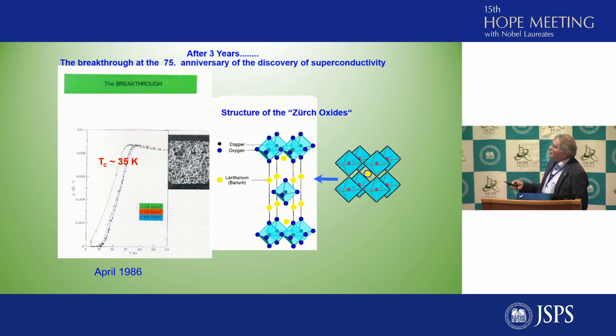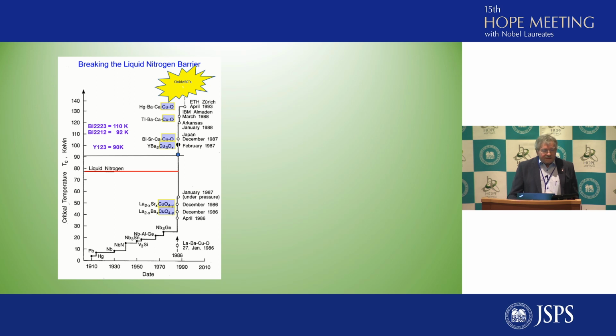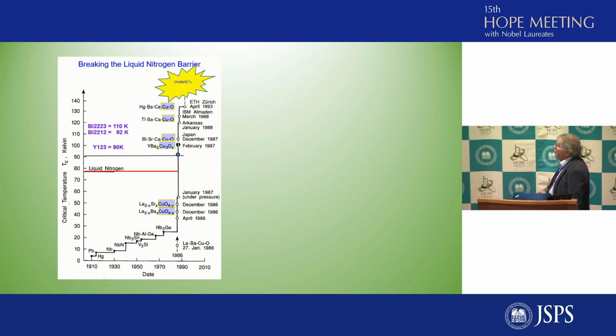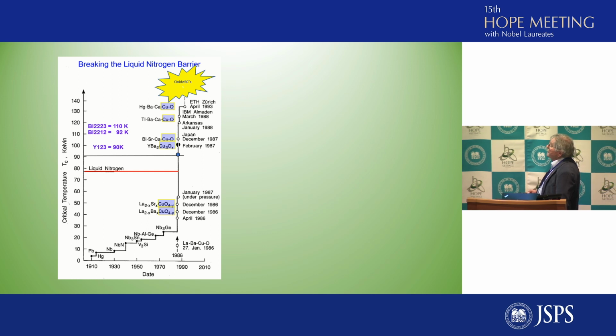Don't worry about the broad transition here, because the samples were ceramic samples and were polycrystalline with a lot of grain boundaries, and it came out later very clearly that grain boundaries can be a big obstacle for the transport of current across. So this sparked a lot of activities in 1987 when our data were published. This is our contribution to the first step in the transition temperatures.